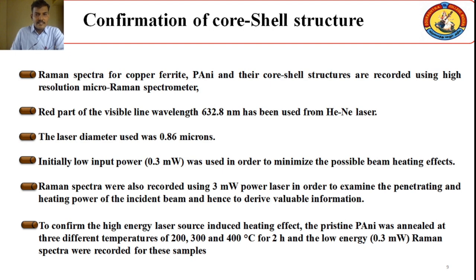As I said, it's the first time we used Raman spectra with different energy values to confirm the core-shell nanocomposites. Here we used 632.8 nanometer wavelength, which is in the red part of the visible range, from the helium neon laser. The diameter we maintained constant at 0.86 microns, and initially we used 0.3 milliwatt of laser power to confirm the outer shell element like polyaniline. Then we used a 3 milliwatt high energy laser to confirm the induced thermal effect as well as the core element.